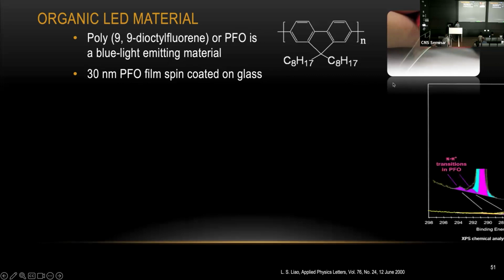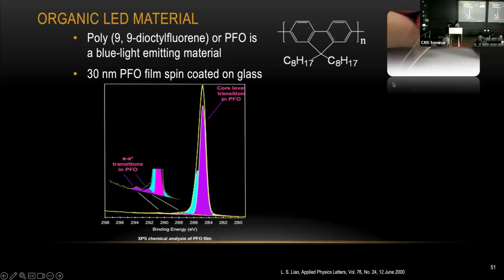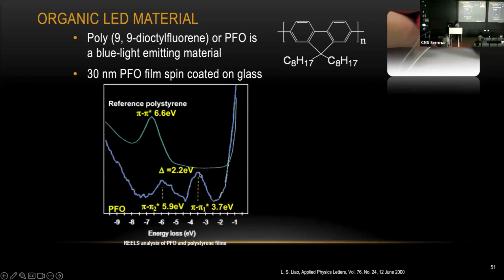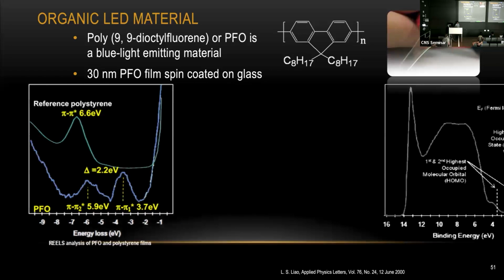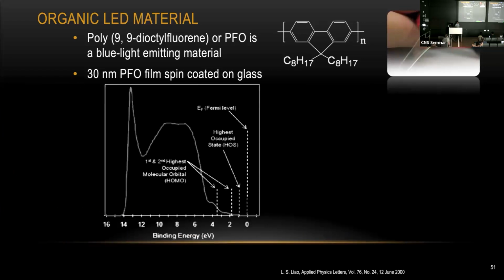So what you can do, first thing will definitely be to do some XPS measurement. You do a survey, see any contamination. Then go ahead and do some high resolution scanning for your carbon and determine all the different kinds of functional groups. Then we will do some measurement for REELS and try to determine the band gap and so on. Then you'll do the measurement using UPS.